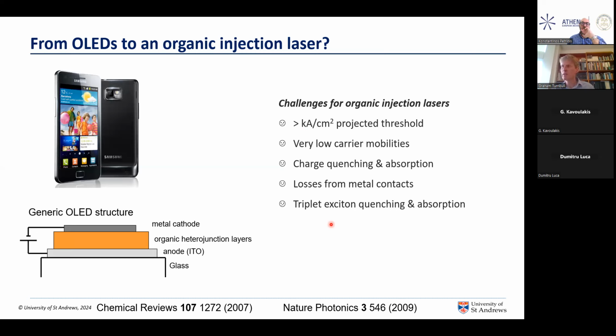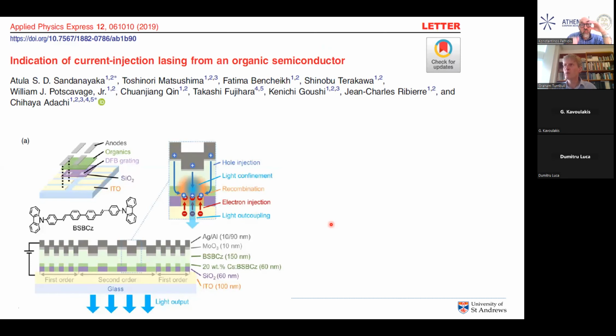But the best that the community has been able to do so far was this work from Chihaya Adachi's lab in Kyushu in Japan about 5 years ago now, where they gave reasonable evidence, but didn't tick all the boxes, for direct electrical injection of an organic semiconductor laser. They had a similar structure, with two electrical contacts, one above and one below the organic semiconductor layer.